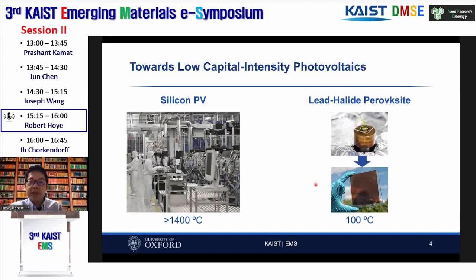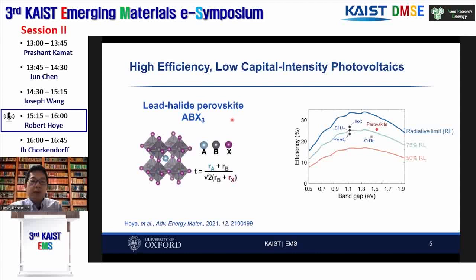I'm sure you heard about perovskites from the earlier talks as well as from your own research, but just very briefly summarizing. What I mean by perovskites are a family of compounds with this crystal structure here. Historically, people have been focused on oxide-based perovskites. But over the past decade, there's been a new class of halide-based perovskites that have been shown to be extremely effective for photovoltaics. It's these halide-based perovskites that I'm talking about. These have lead cations coordinated octahedrally with halides to form this cubic perovskite unit cell. And in the cuboctahedral vacancies, we have a large A-site cation. This can be an inorganic cesium cation.